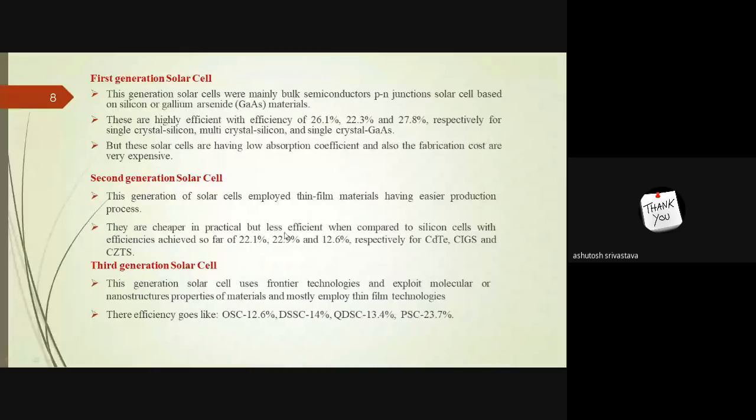And the very prominent and very emerging technology that I was talking about was CZTS based solar cell, though it has only nowadays 12.6% of efficiency. But yeah, it is being explored a lot because the efficiency chart of this cadmium telluride and CIGS has gone almost to a stagnation stage. And also the presence of these not good materials like cadmium and indium has made this research shift towards this CZTS technology, because it has lots and lots of perks as compared to the previous one, two technologies. Moving on to this third generation solar cell, we can see there's all this efficiency.